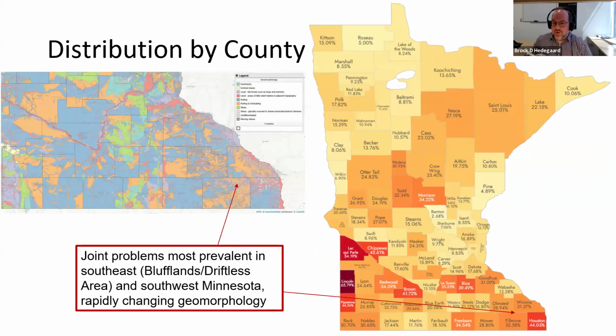We also wanted to look at the geographic distribution of this by county throughout the state. So you can see on the right, we have a plot of the state of Minnesota, and the darker the color in general, the more percentage of the concrete pipes in that county have joint separation. So for example, you can see a couple concentrations of separation. There's a few right here in central Minnesota, but most of them are going to be actually down in the south part of the state. So for example, in the southeast region, so in the driftless area down here, we have quite a bit of separation down there. And then also over on the southwest side.